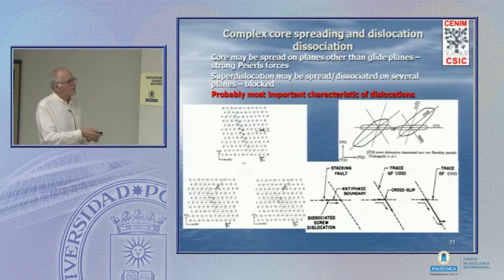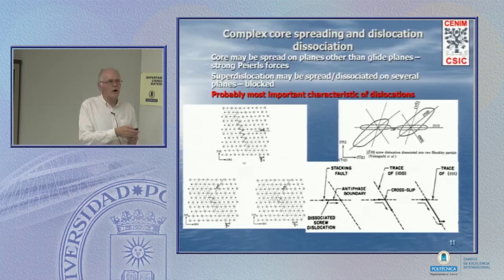Now if I look at the core of the dislocation, and this is a little bit esoteric, but I've put here in red what is probably the most important characteristic of these dislocations in intermetallics, or if you like in ceramics as well. Here's a super dislocation made up of two cores with a stacking fault in between. And the cores plus that plane, the stacking fault, defines the plane of easy movement of the dislocation. The core itself is not a point object, it elastically relaxes. This dimension is something like 1 nanometer.